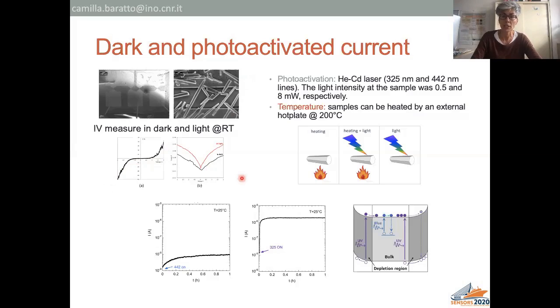And in the sensing test, our approach was to activate the sensor by means of heating with a hot plate put in the test chamber, and also by shining light, and both. The light used was a helium-cadmium laser, both the blue and UV light.